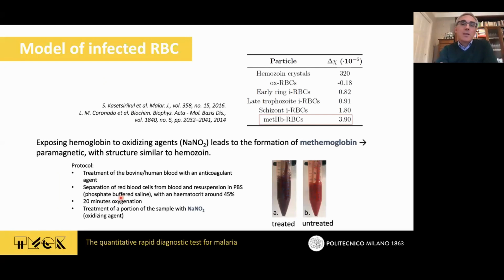So we use this model for the infected red blood cell, which is based on the transformation of hemoglobin into methemoglobin. As summarized here, the relative susceptibility of red blood cells treated with this strongly oxidizing compound, sodium nitrite, is 3.9 × 10⁻⁶, which is not too far from that of the schizont-infected red blood cell, which is 1.8. In this way, we were able to characterize our magnetophoretic platform and also our detection platform.